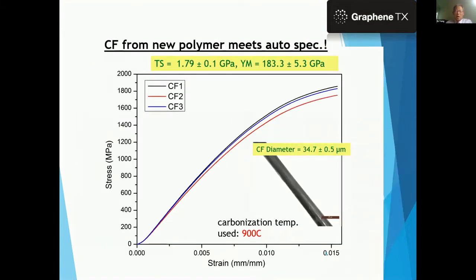And then we only use 900 degrees C, and the diameter is still not as thin as 7 micron, but using a 35 micron diameter at a 900 degrees C carbonization temperature, we will be able to meet automotive spec. Okay. And then, of course, if we reduce the fiber diameter, and also if we increase the carbonization temperature, we will exceed the performance as I show here.